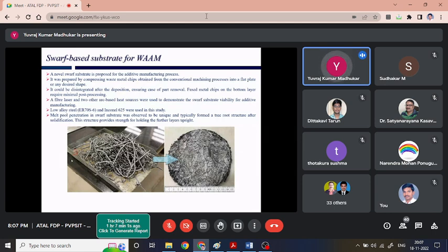If we reach this stage, another innovative idea we came across is this. The result of conventional machining is nothing but a wastage of metallic chips. So what we did, we collected these metallic chips from our central workshop, and then compressed them using some sort of a die punch mechanism, ensuring the thickness of the order of nearly 5 to 7 mm, and ensuring the density of the plate, or this porous structure, of the order of nearly 40 to 50% of the solid metal plate.